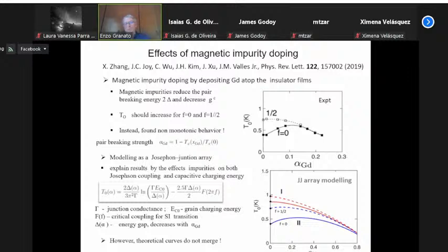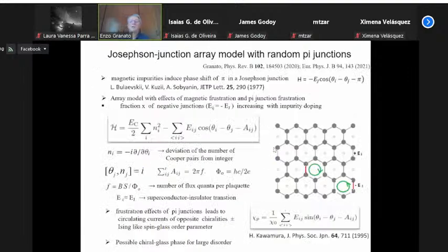So we were particularly interested in this behavior and want to describe the array model with some modification and describe the experimental data, including this merging of the transition. For that, we use again the same model we used before. But there is no magnetic flux disorder; instead there is a disorder in the junction itself, because the magnetic impurities, which are deposited in the cross sections, can fall inside the junction itself. And the magnetic impurities in the junction can induce a phase shift of pi in the Josephson coupling.